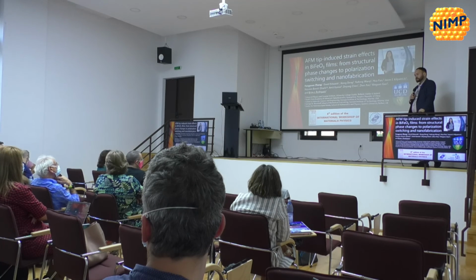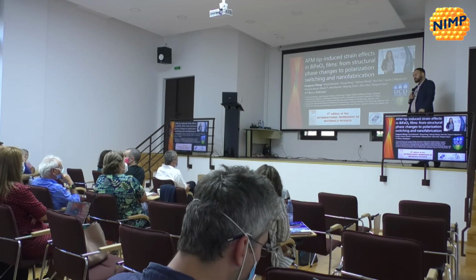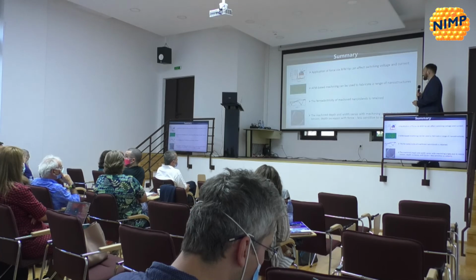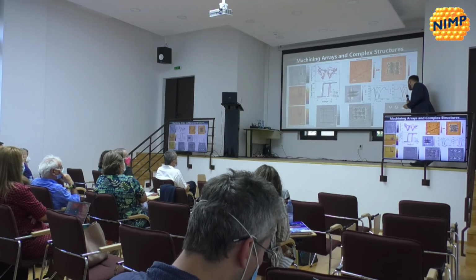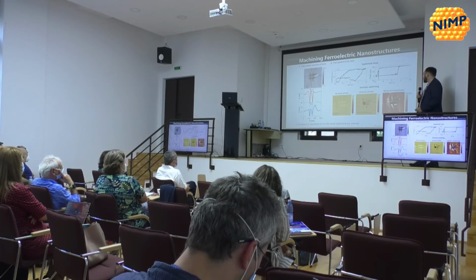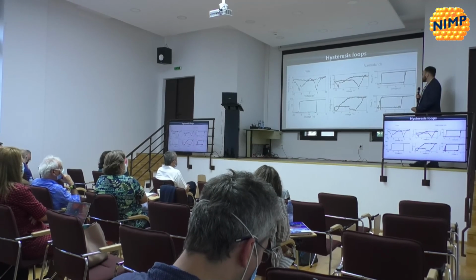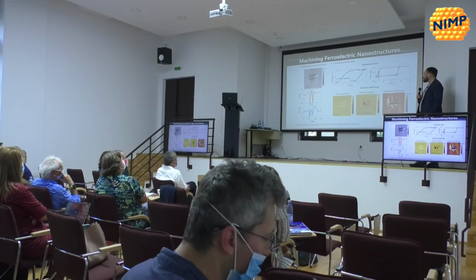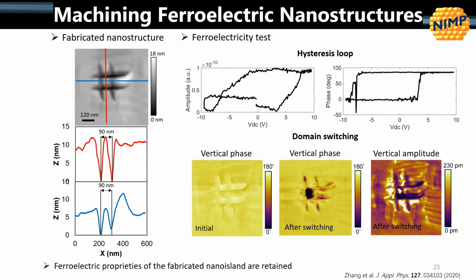Brian, when you show machined ferroelectrics, I think it was slide 24, there were loops. Do you think that this asymmetry, so some of the loops are asymmetrical, meaning that d33 in one direction is weaker than in the other, is a genuine asymmetry, or does it really represent the presence of some secondary phase or something? Yeah, it's a good question. It's hard to really know, and we didn't apply mapping of switching loops in this case. So we didn't use BEPS or anything like that to see if there's a variation in the switching properties across.